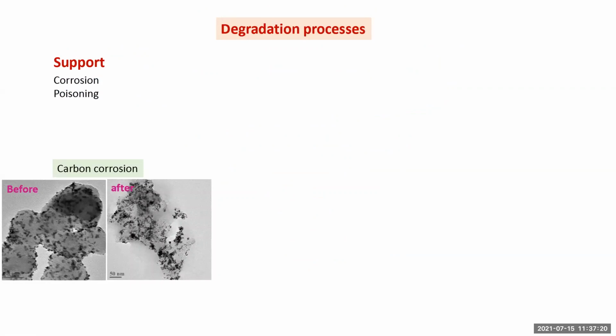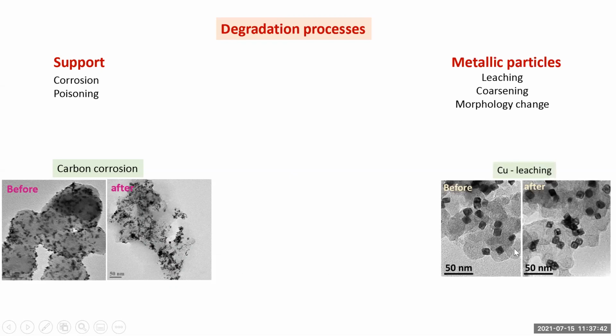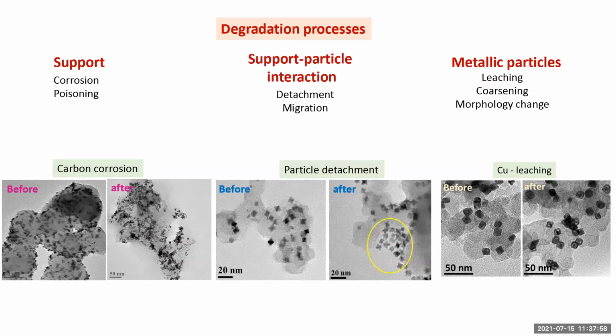If the particle or the catalyst has a degradation process, the activity will decrease and be destroyed, and it's not useful for research nor useful for the industry. So some problems can happen in the support, it could be corrosion of the carbon, it could be poisoning, it could also be the degradation of the particles. So usually if we use nickel or copper, the transition metal leaches, and this is a very common problem, but also coarsening or collapse of the particle.